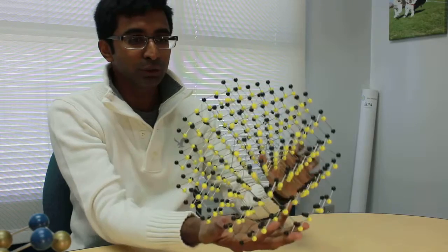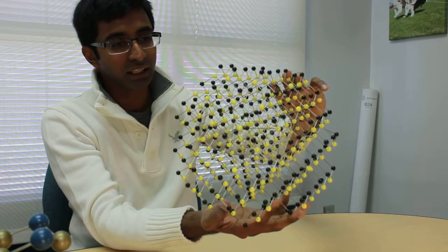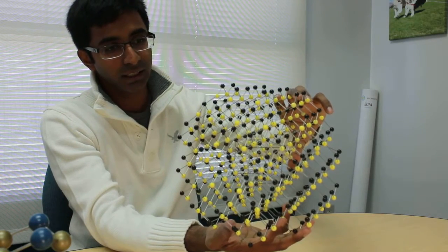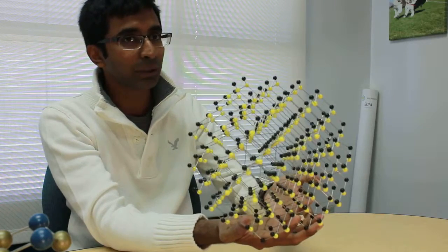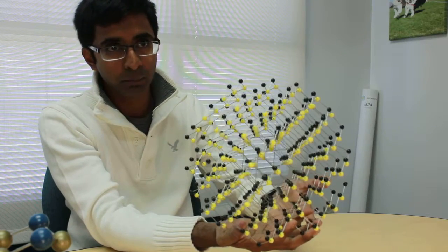And what you do is the topmost layers, about I would say 80% of your spectrum, is absorbed in pristine defect-free lattice-matched semiconductor. The last 20% is absorbed in the metamorphic material, and it's found that it doesn't cause too much degradation to the efficiency of the solar cell, and you can get away with it.